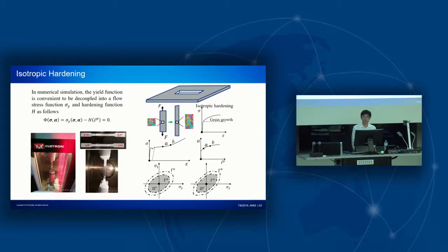By cutting a coupon from a rolled sheet and putting it in a specimen, applying some loads, and then we can measure the loading and the displacement relationship. And then we can convert the loading and displacement curve into the flow stress and effective plastic strain curve. And using that, we can calibrate our isotropic hardening, which is just the hardening function H.